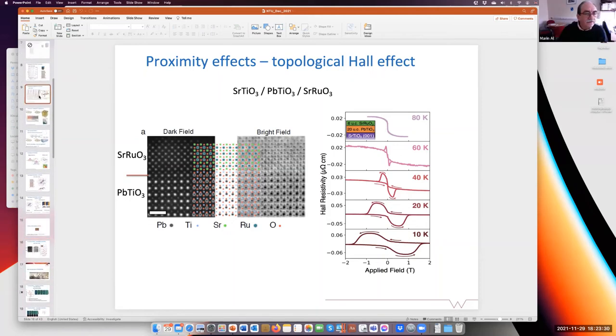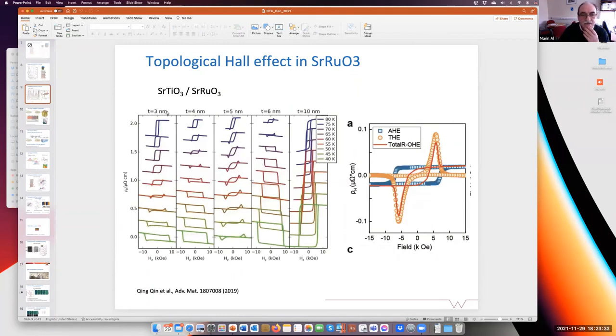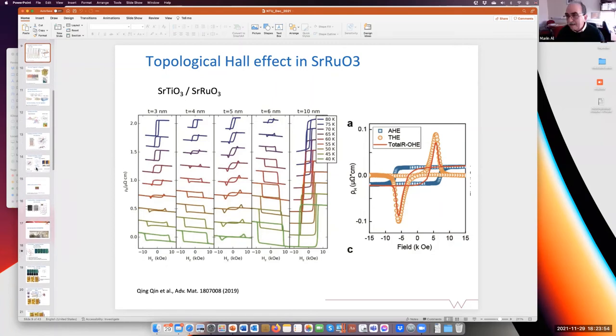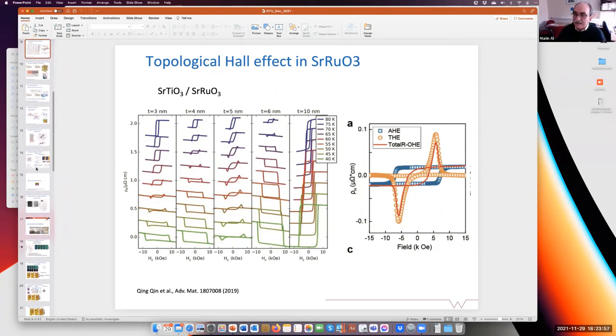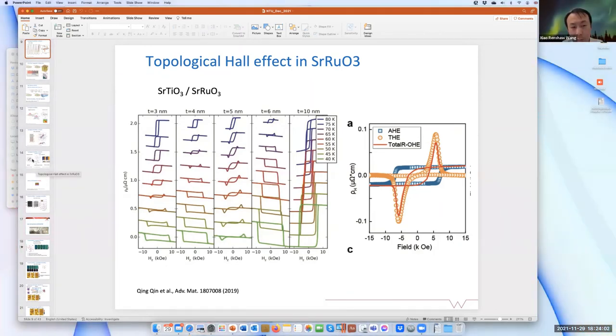Other work, so if you see here, that's a thickness dependence. This is on strontium ruthenate, the bare strontium ruthenate. And then you see it's coming around this temperature, which is 60, 70 Kelvin, 80 Kelvin, yeah? So that means it's way below the TC of strontium ruthenate. Exactly. So I don't think that strontium ruthenate has much influence from that point of view. So STO may play a bigger role. It could be, it could not be, have no idea.